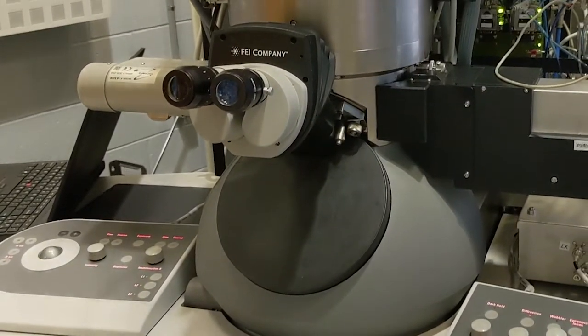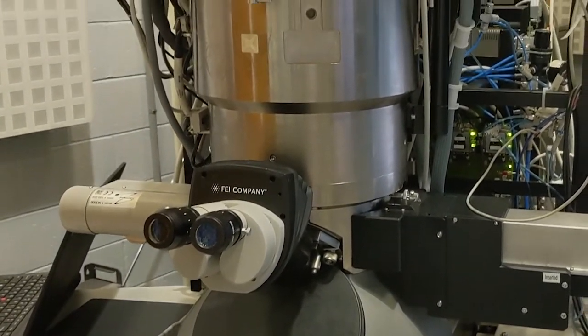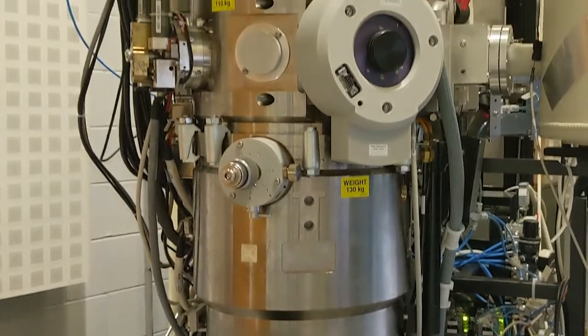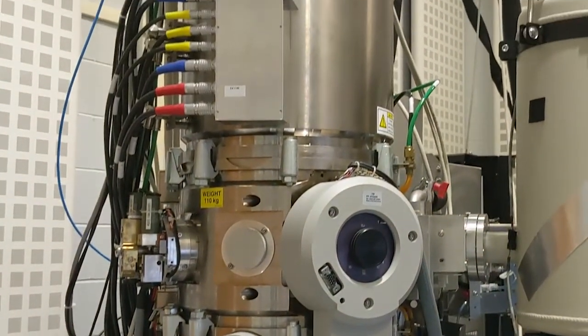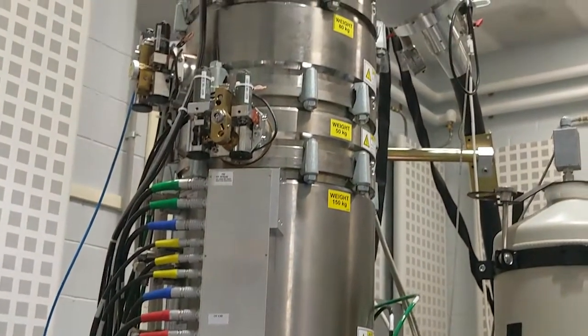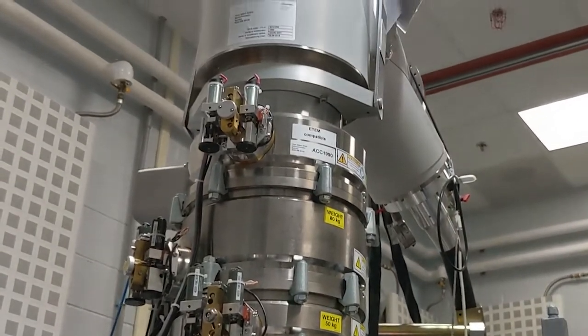Hello, my name is Christopher Winkler, and I am the TEM lab manager here at the Analytical Instrumentation Facility. I'm sitting in front of one of 3 TEMs that we have in our facility. This is the probe-corrected monochromated Titan. The 4D STEM detector on our Titan allows us to collect a diffraction pattern at every probe position on our sample. We can process these diffraction patterns to look at things like strain, different phases, chemistry, and many other interesting parameters regarding our samples.